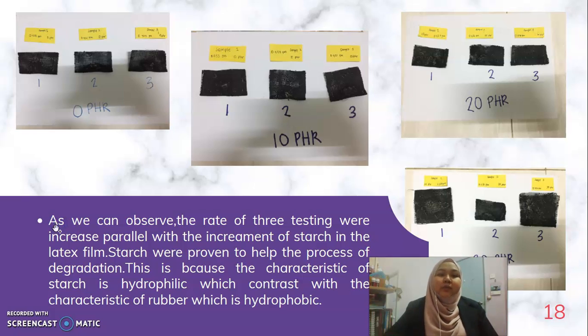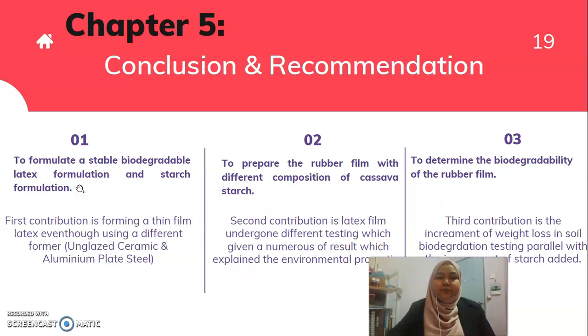Okay, as we can observe, the rate of the 3 tests increases in parallel with the increment of starch in the latex film. Starch was proven to help the degradation process. This is because the characteristic of starch is hydrophilic, which contrasts with rubber, which is hydrophobic. So we move to the next chapter, Chapter 5, Conclusion and Recommendation.